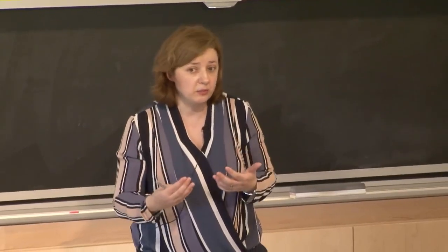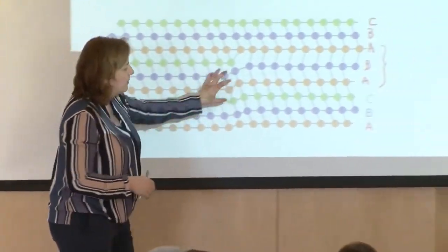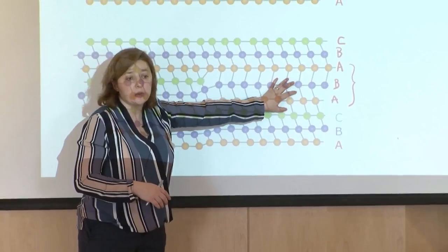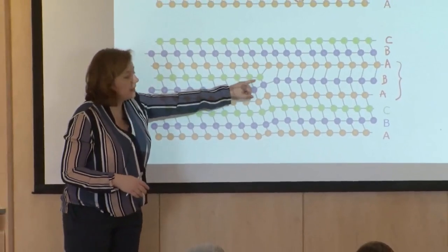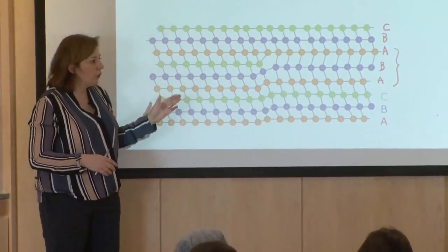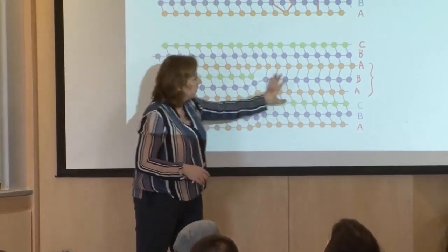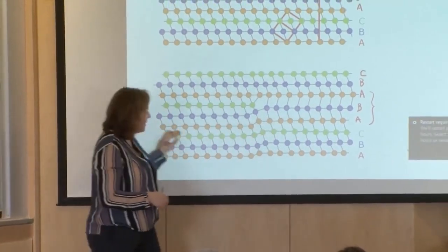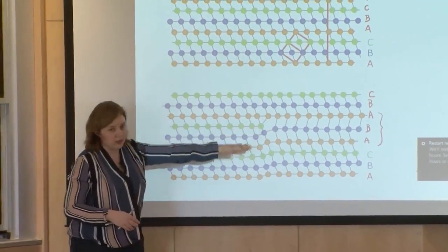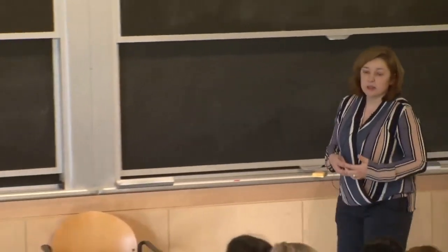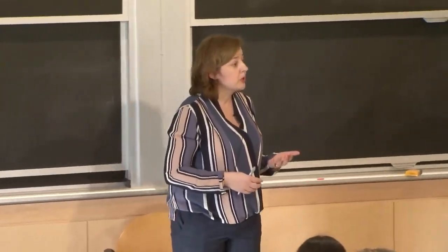This is one mechanism of formation. What is really important to notice here is that locally you do have a stacking fault within the bulk of the material, but then it has to be surrounded, or edged, with an edge dislocation. One thing that you will notice is that on the left-hand side, the stacking fault does not exist, right? On the right-hand side, the stacking fault is here, but then this region here ends up with an edge dislocation. And it turns out that these edge dislocations that are connected and related to stacking faults are called partial dislocations.